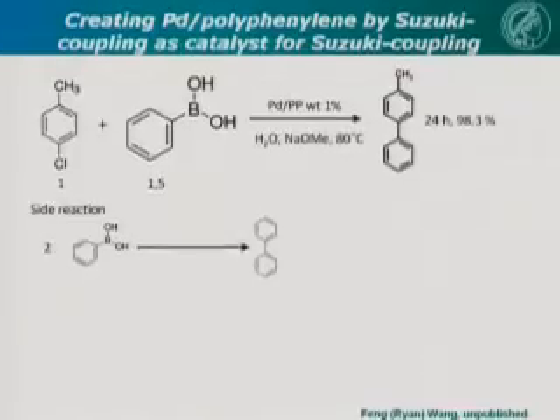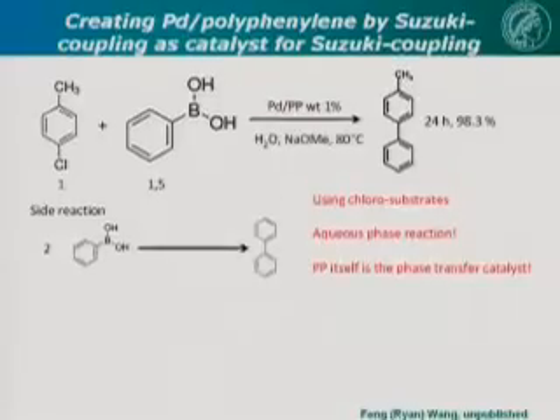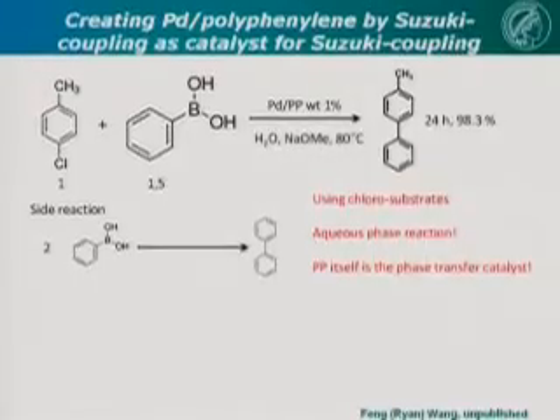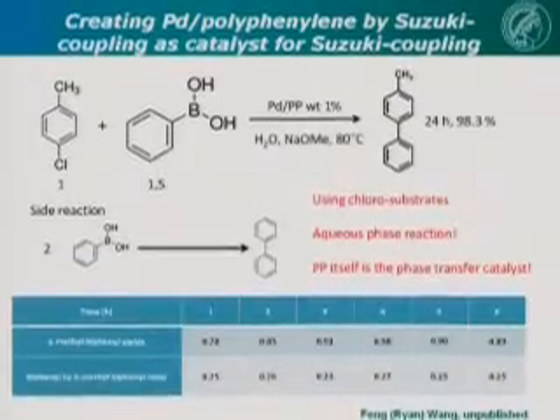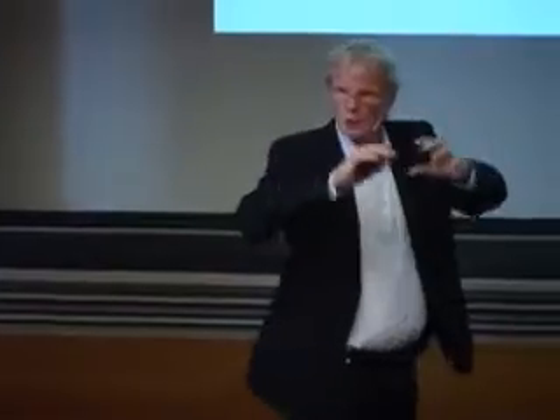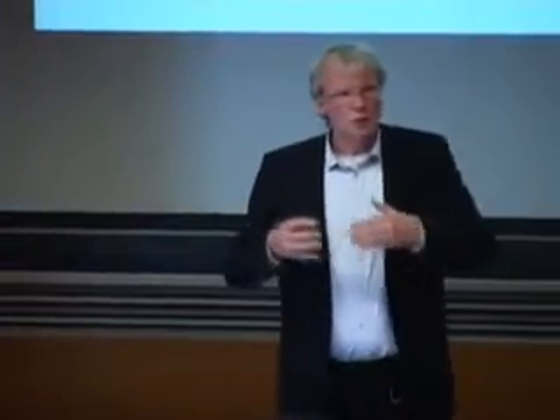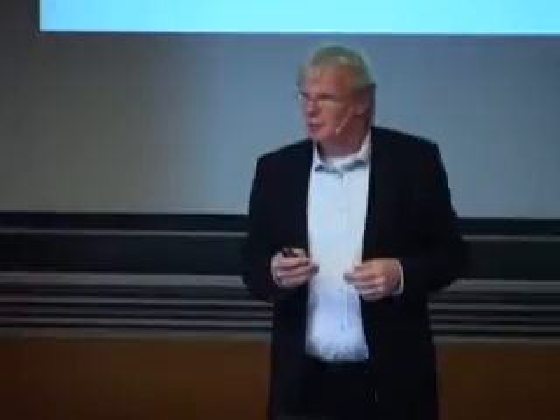We have a side reaction, the coupling of the boronic acid with itself. But if you look at it, we can activate chlorosubstrates with this catalyst. It's just aqueous phase. We don't need a phase transfer catalyst. It happens all in the porous polyphenylene, and you can recycle several times without much loss of reactivity. So I think this is quite an interesting concept, to place noble metal particles in a pore system by a reaction for which you then later catalyze by the catalyst created.